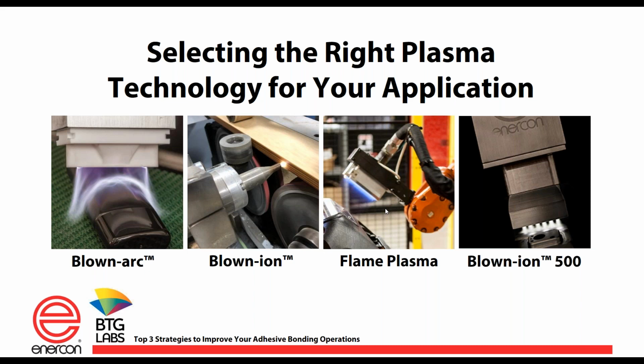So that's why you see it used on door panels and dashboards, because those are very multidimensional. You're going to have a lot of different areas, and the flame plasma gives us about a 4 or 5 inch area where we can get good, consistent treatment without actually controlling the distance from the head, or the burner in this case. You know, Wilson, one thing I want to jump in on, the thing that I like about that is it just reduces integration cost, because if you don't have to program for a real tight Z dimension to the part, then you've got more room to play. You literally have to spend less time programming.